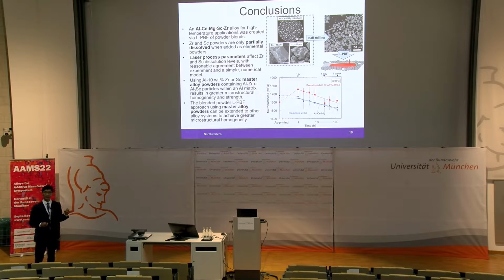We then replaced the elemental powders with master alloy powders, and this resulted in greater microstructural homogeneity and an improvement in mechanical properties. And lastly, this approach should not be limited to just this alloy, but should also be extended to other alloys manufactured by similar processes.